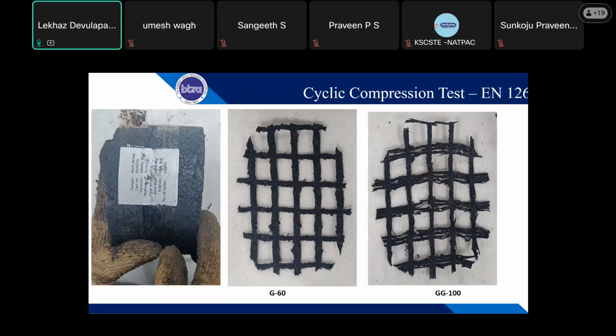So after the test was done, we checked the geogrids, how they were after placing, and whether there was any damage to the geogrid. Then we exhumed the geogrids without damaging them by placing the specimen in an oven at 60° for 4 to 6 hours, and then we split the specimen to check the damage. You can see the polyester geogrids are good and intact. Some particles like asphalt and the tack coat are visible.